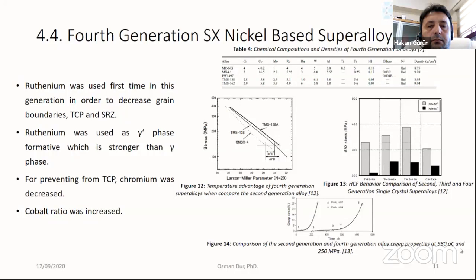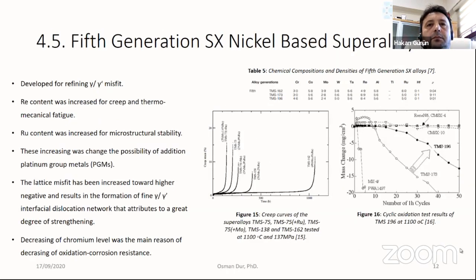As you see in the figure, TMS-138, a fourth generation superalloy, is better than the other generations when compared for fatigue and crack performance. Also, PWA 1497 was better than PWA 1480 for crack properties. This generation was developed for refining gamma over gamma prime misfit. The rhenium content was increased for creep and thermomechanical fatigue. Ruthenium content was increased for microstructure stability. This increase changed the possibility of adding platinum group metals.